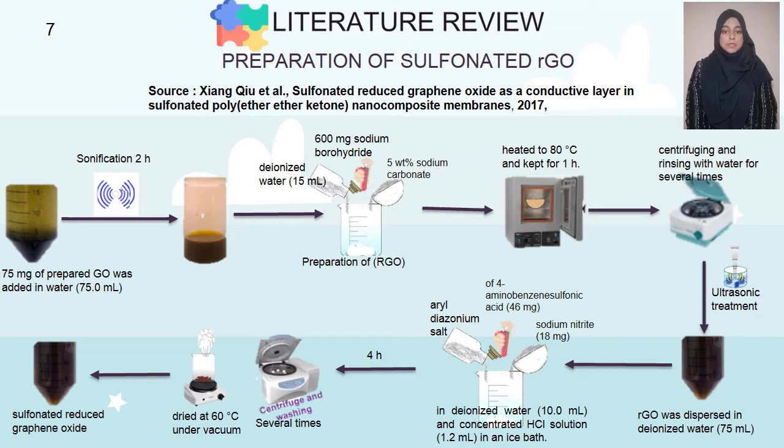After 4 hours of reaction, the sulfonated reduced graphene oxide was centrifuged and washed with deionized water several times and dried at 60 degrees Celsius under vacuum.